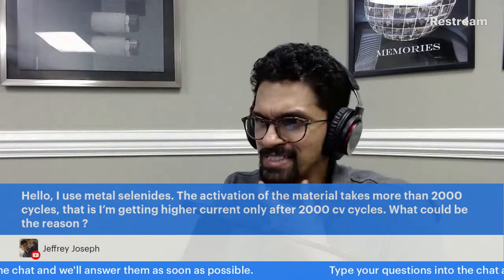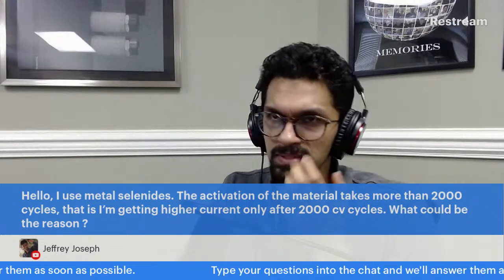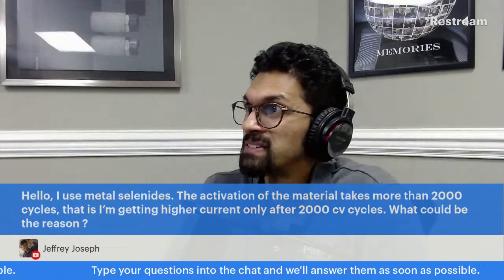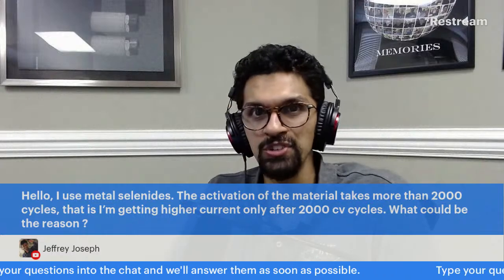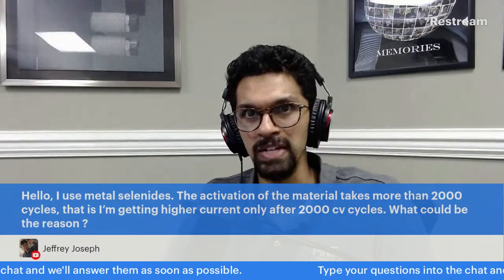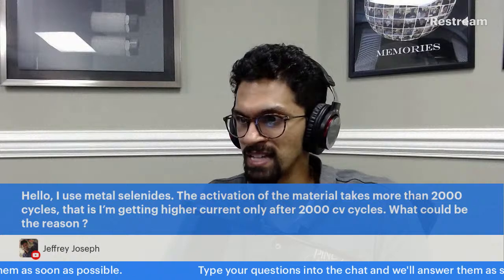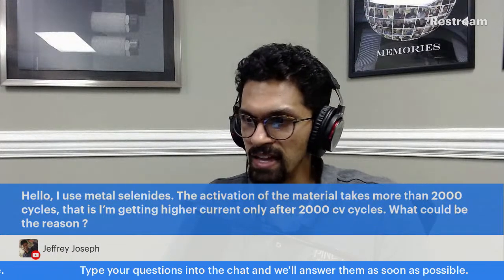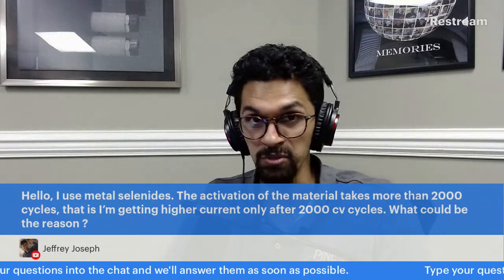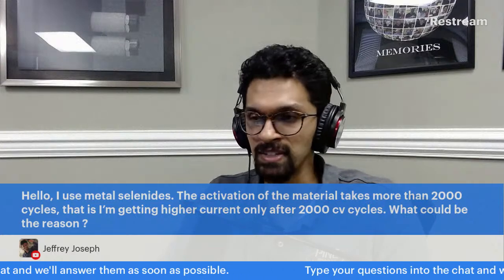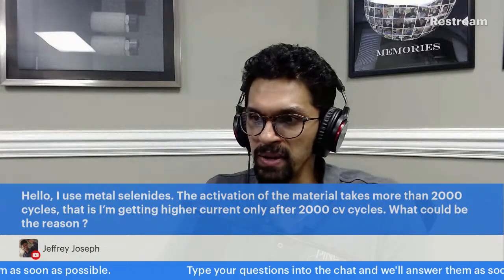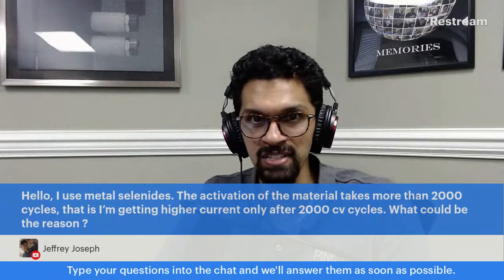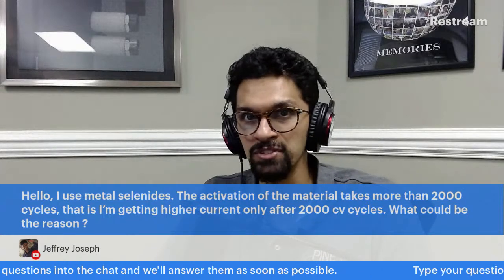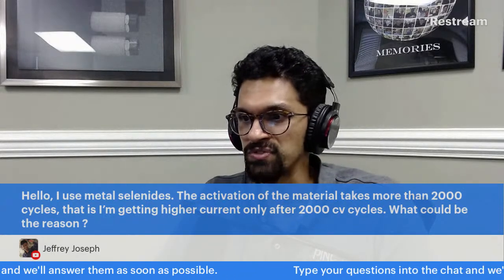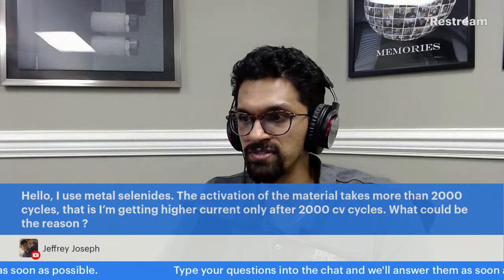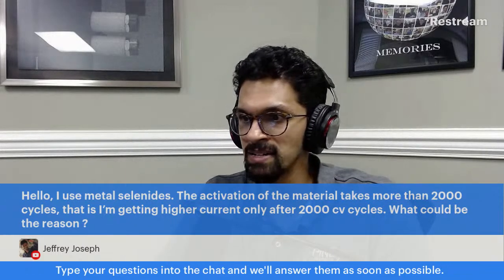So the nature of activation usually has to do with something on the surface that's not allowing reactivity to your metal selenide. And it's only after 2,000 cycles that you're able to remove that thing that's unactivated. I'd be curious to know whether you have a way of cleaning the metal selenide, like polishing it, removing stuff that could be on the surface. Something is on the surface that's very difficult to get off, is what it seems like.